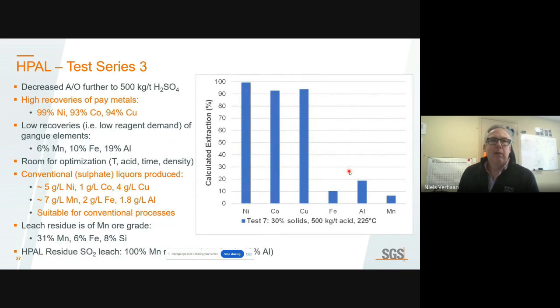So we ran another series of tests, reduced our acid addition further. We were operating at high pulp density, 30%. And this test we were quite pleased with. So we had high, almost quantitative extraction of nickel, 99%, kind of mid-low 90s for cobalt and copper. And we were able to show that we were able to reject the majority of our impurities. And those are the impurities that contribute to our reagent demand, manganese, iron, aluminum. We were able to reject those into the leach residue.